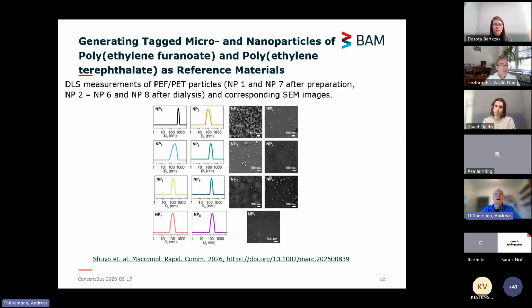Here you see an overview of these different particles. All the particle size distributions are monomodal. Some of them are already very narrow, but all are monomodal. And as I said, if nanoprecipitation was used, then the particles are close to spherical, and if mechanical degradation is used, the particle surfaces are very rough.